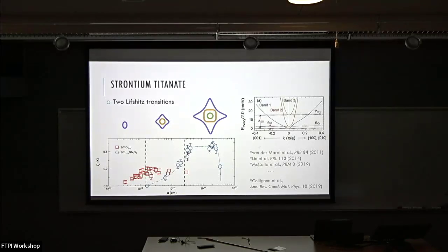Okay, and then the second important point is that there are actually 2 Lifshitz transitions. So the band structure has 3 bands. And this is due to a combination of this tetragonal splitting and spin orbit coupling. So in the lowest doping limit, you only have 1 band, then there's 2, then there's 3. And as you can see, this outer band, especially, is very far from a sphere. So it has this quite complicated shape, which again will be important for us as we move on.